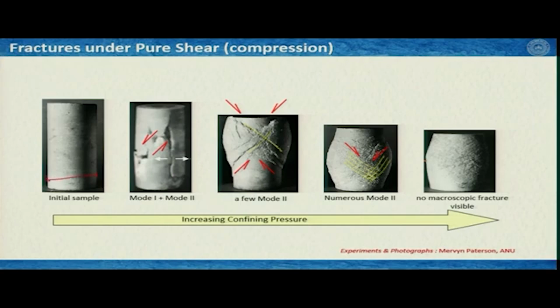The diameter of this sample was 15 millimeter, and from here different experiments were conducted with increasing confining pressure, and as you can understand from the shape of the samples, these samples were compressed. What we see here, when the confining pressure is very low, is that opening mode fractures are appearing. Opening mode fractures here and shear fractures here, and they are less in number.